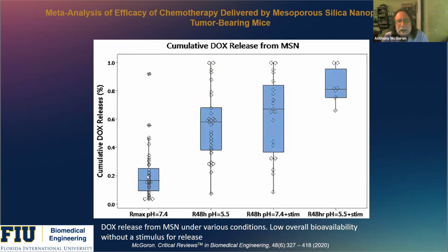And one issue is the release rate. So we've got an issue of the drug actually making it to its site of action, but the other issue is whether or not the drug is actually being released. So for these mesoporous nanoparticle formulations, the release of doxorubicin is generally low, at least in normal pH, which is good in the sense that we don't want premature release in the plasma, which is roughly at a pH of 7.4. And then the idea is that when it reaches the tumor, and most of these particles get taken up through endocytosis, when it makes it into the tumor, the release is faster. But still, there's a huge distribution.